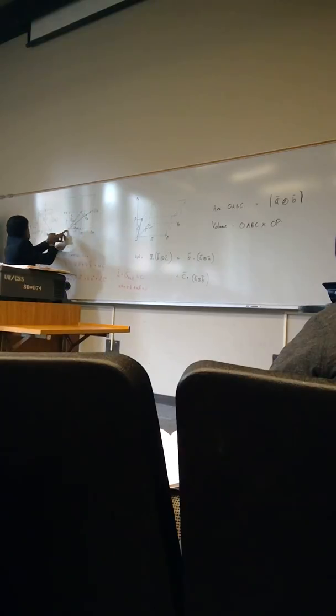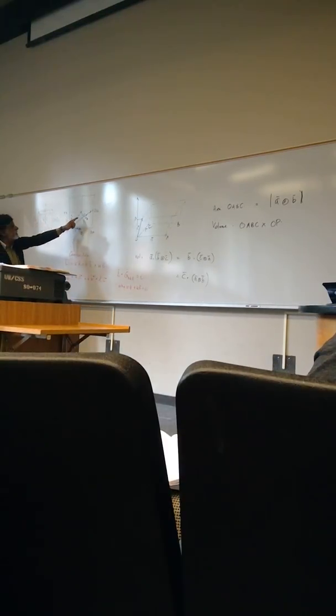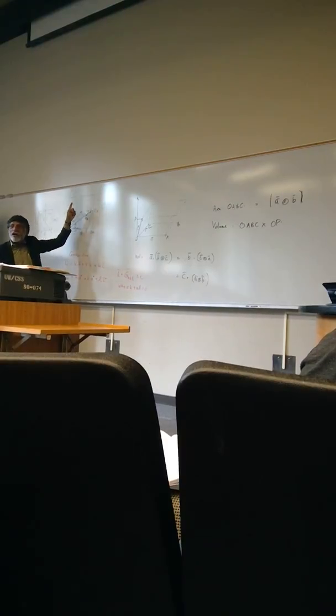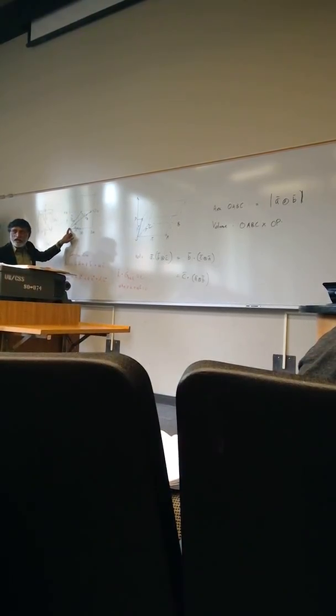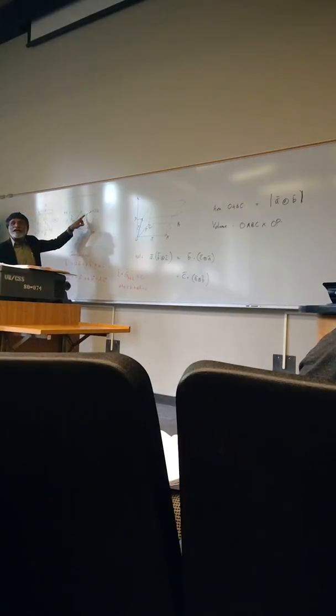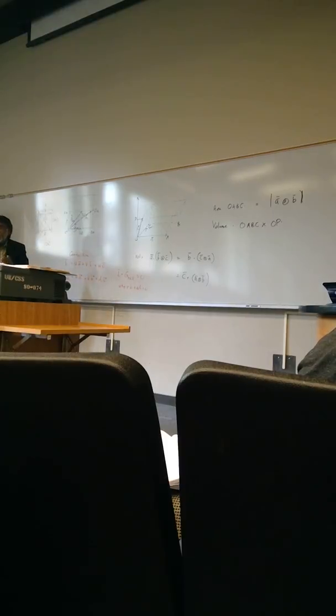So this is the reciprocal. Just like you created a real lattice by a set of vectors A and B and C, these reciprocal lattice points can also be represented by a set of arrays of points, and you can describe them as vectors from the origin. This is the reciprocal lattice. Okay. So when you say G_210, it tells you that it has a certain magnitude, and the magnitude is the reciprocal of the interatomic spacing, and its direction is given by this. That's normal to those set of planes.